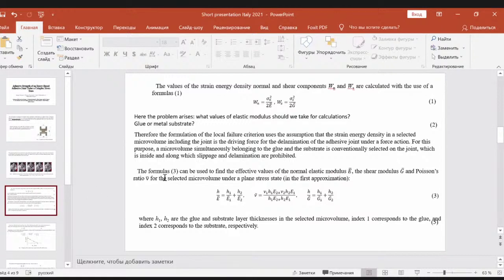The values of strain energy density, normal and shear components, Wn and Ws, are calculated with the use of formula 1. Here the problem arises. What values of elastic moduli should we take for calculations? Glue or metal substrate? Therefore, the formulation of the local failure criterion uses the assumption that the strain energy density in a selected microvolume, including the joint, is the driving force of a delamination of the adhesive joint under the force action. For this purpose, a microvolume belonging to the glue and the substrate is conventionally selected on the joint, inside and along which slipping and delamination are prohibited.